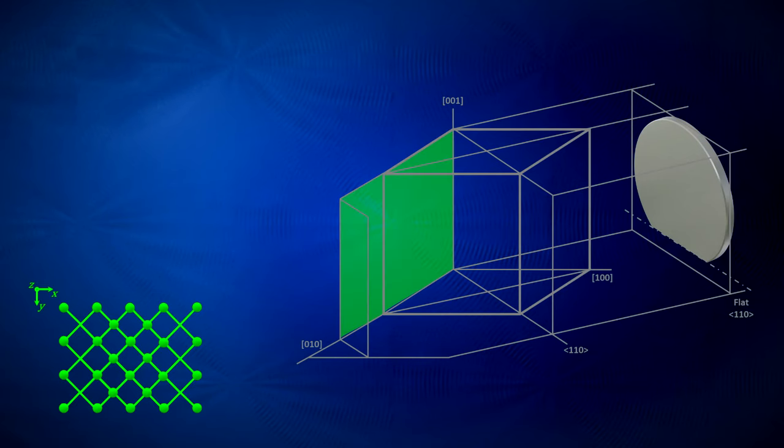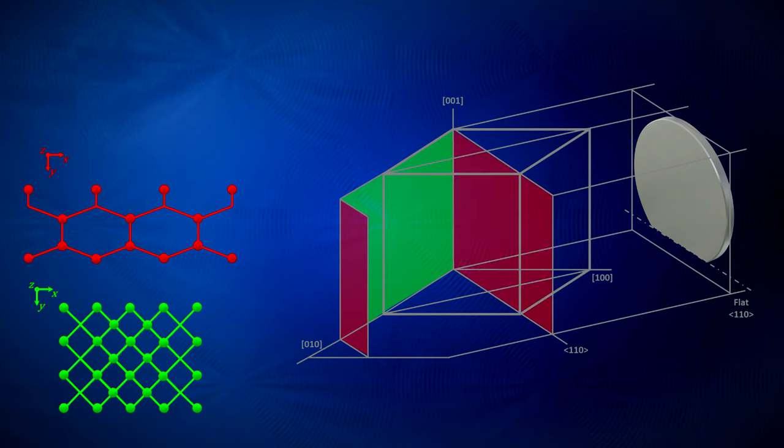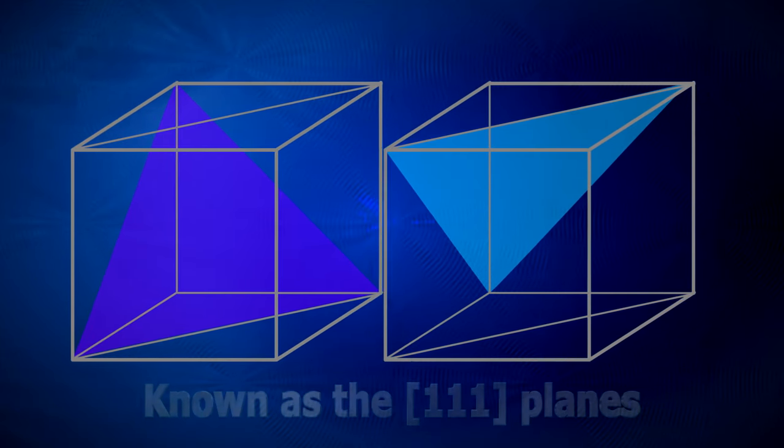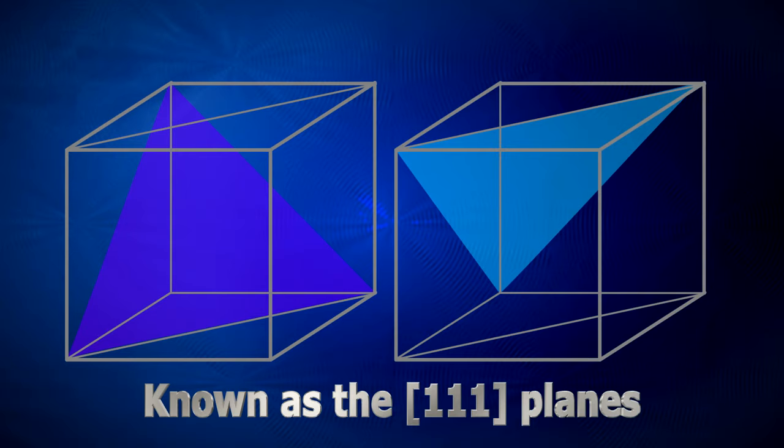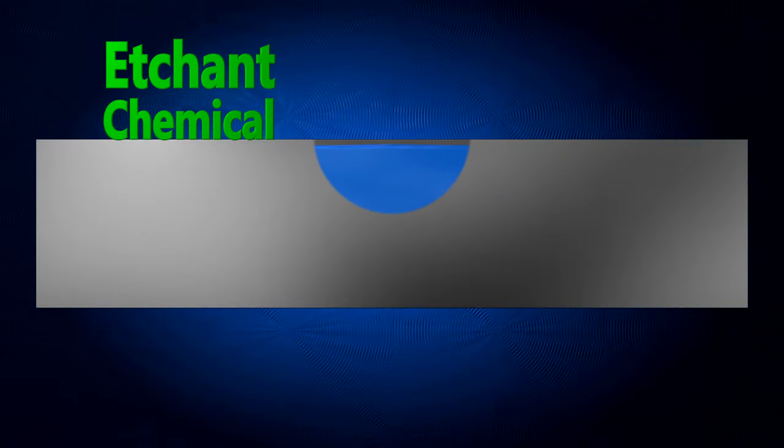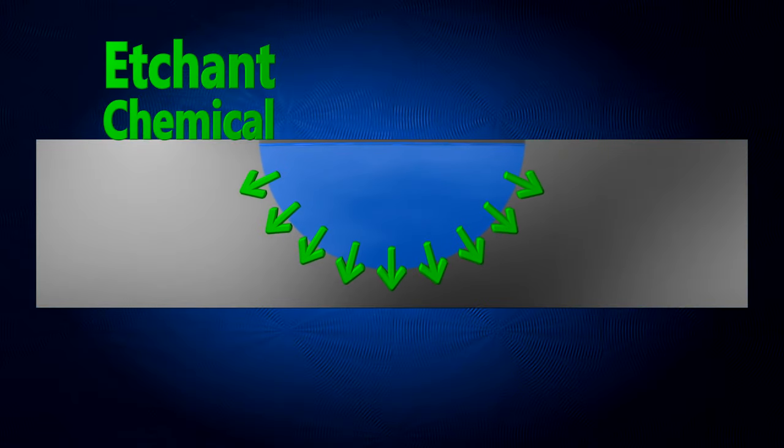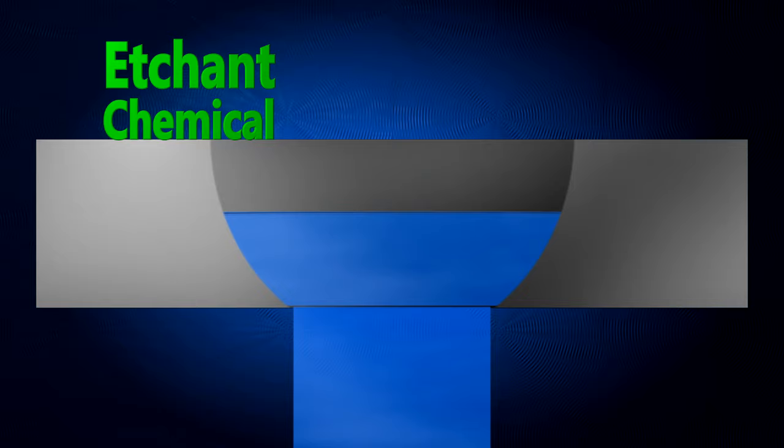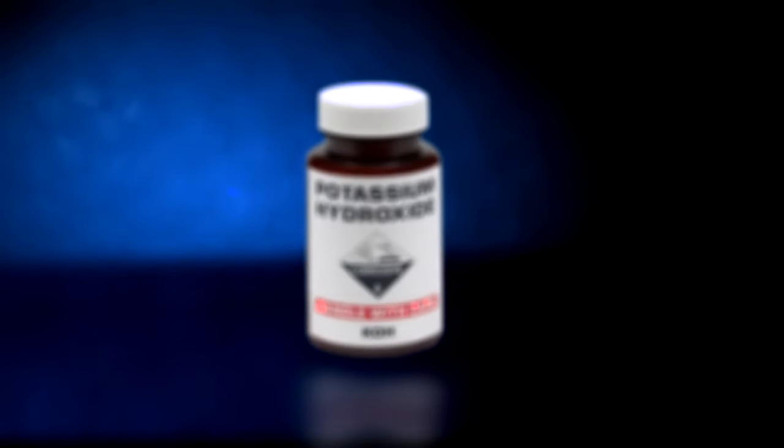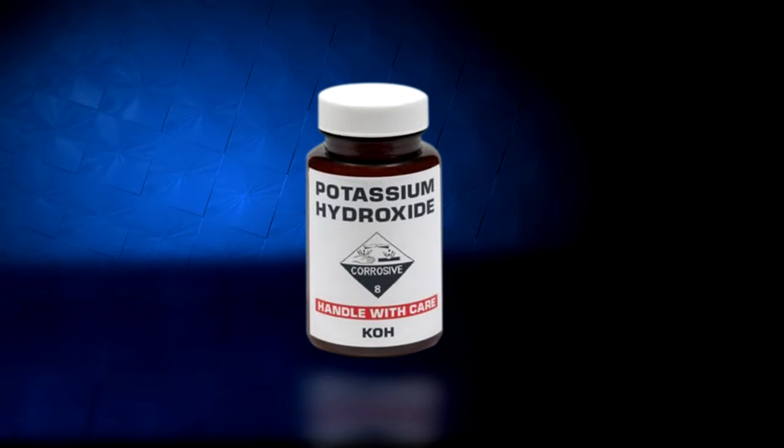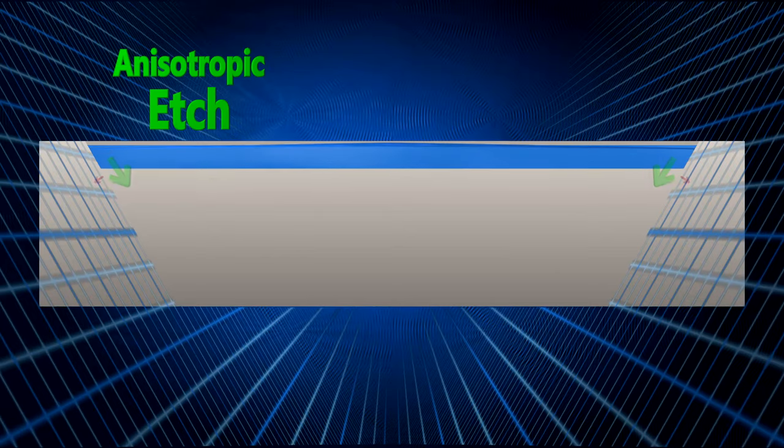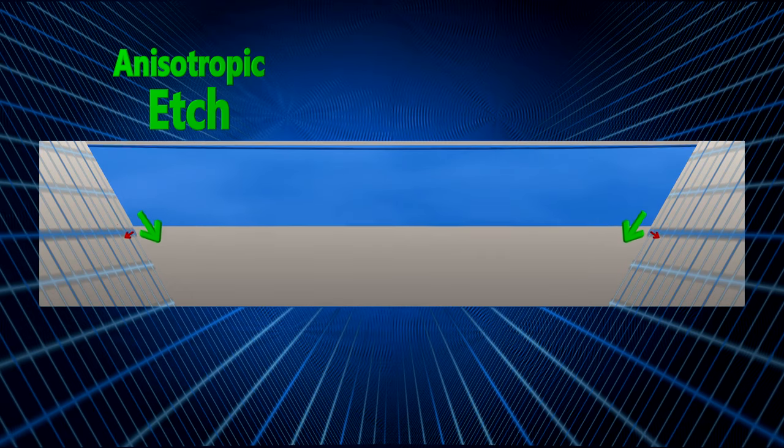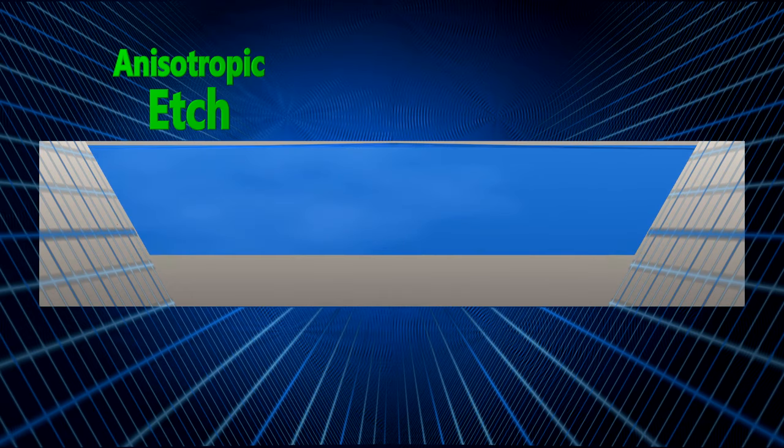Crystal planes are simply repeating patterns of silicon atoms in the crystal structure and they each have different properties. Hey let's talk about these two planes. Whereas most chemicals intuitively etch out in all directions, some chemical etchants, for example the very popular potassium hydroxide, etch 400 times faster parallel to these planes than perpendicular to them, allowing engineers to carve out near flawless pyramids into silicon.